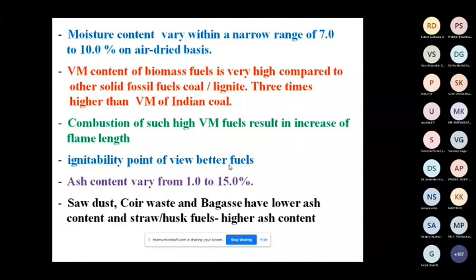So the overall overview: the moisture content varies within a narrow range of 7 to 10% on air dry basis for biomass fuel. The volatile matter content of biomass fuel is very high compared to other solid fuels like coal or lignite, almost 3 times higher than Indian coal. We have seen 23% for coal, whereas here we have around 70% for biomass fuel. Combustion of such high volatile matter fuels results in an increased flame length. From the ignitability point of view, it is a better fuel. Biomass fuel is better than coal because of its high volatile matter; it can be ignited easily.